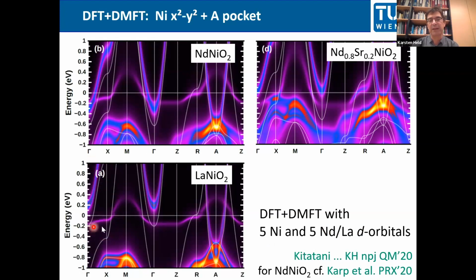The spectral weight is also a little bit lower because, of course, you form Hubbard sidebands. Now, you see the x squared minus y squared orbital is strongly correlated. There's also the A pocket, which is very stable and always there. And then there's the gamma pocket. The A pocket, white line, and the false colors are essentially on top of each other, so there are no strong correlations. And also for the gamma pocket, it's more like a Hartree shift, what you have here, but no real strong correlation effects, what you see for lanthanum nickelate.